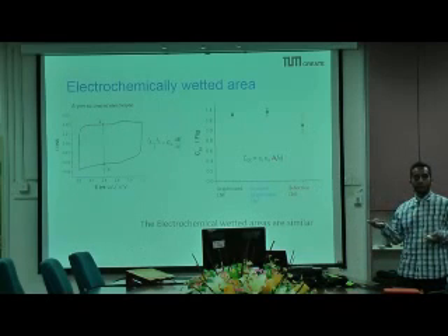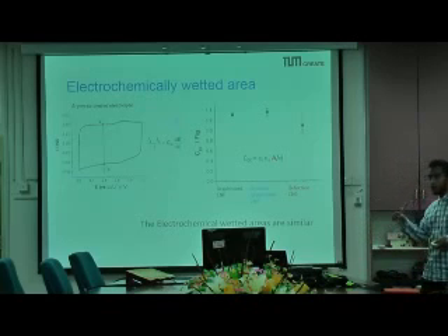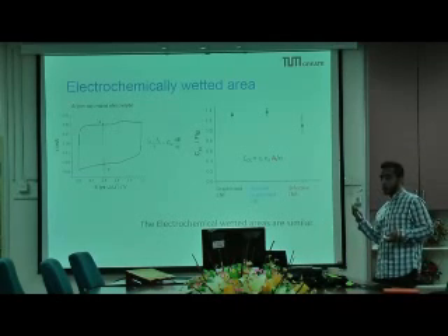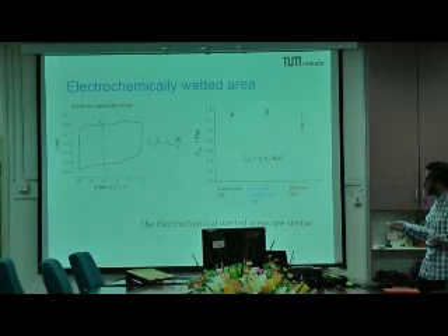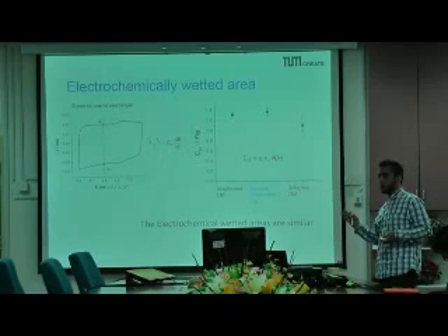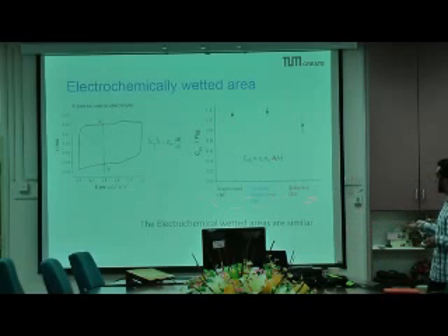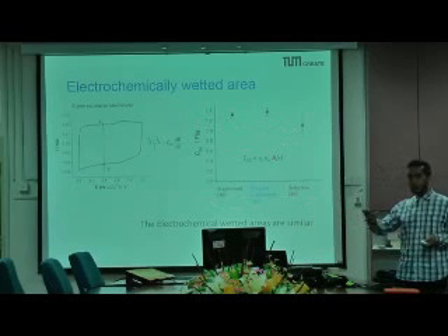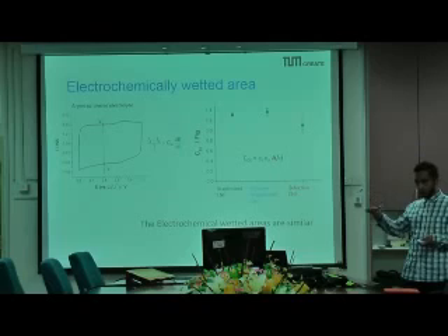I think people working in catalysis will know that if you increase the surface area, your activity will increase because you have more active sites. So to verify this, what we did is measure the double-layer capacitance. The double-layer capacitance literally means the electrochemical area, which is different from BET. BET measures in a condensed nitrogen isothermal system. So in the capacitance measurement, what you measure is the amount of electrolyte charge or ions that is touching the electrode surface. If you plot these two different materials, we end up with rather similar capacitance, suggesting that the area is the same. So what we're changing is the amount of defects, or in this case, the active sites.